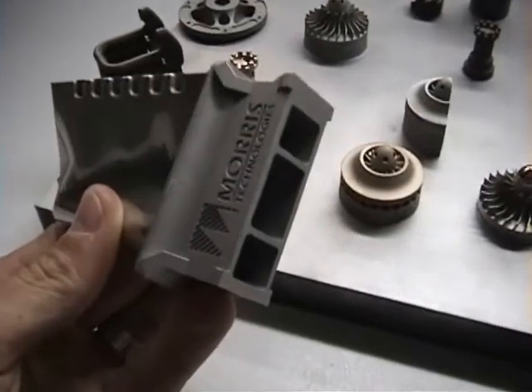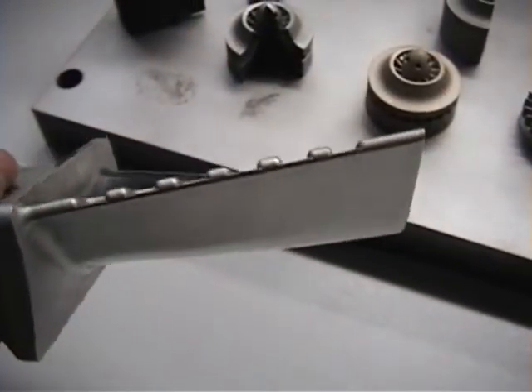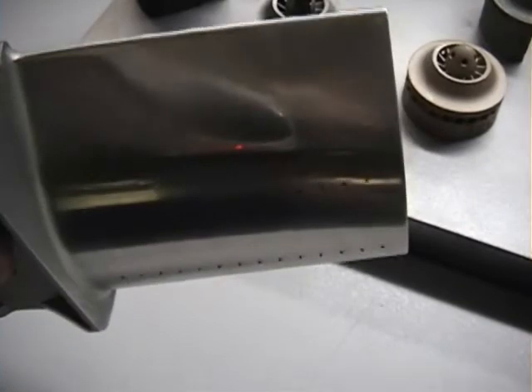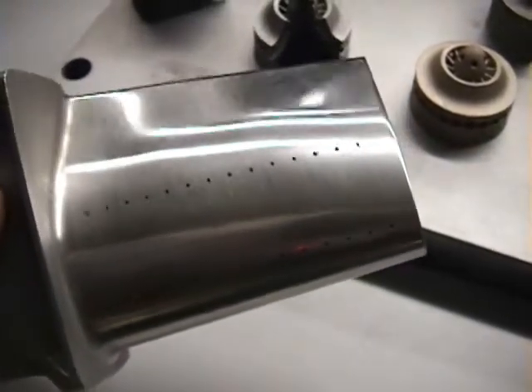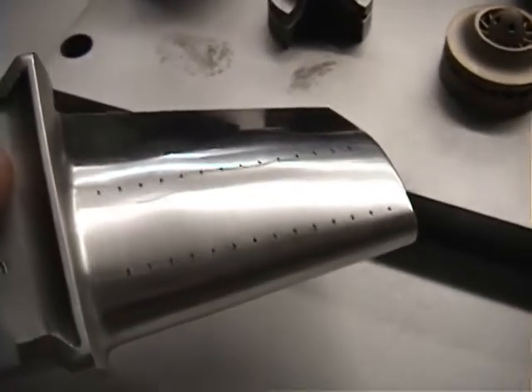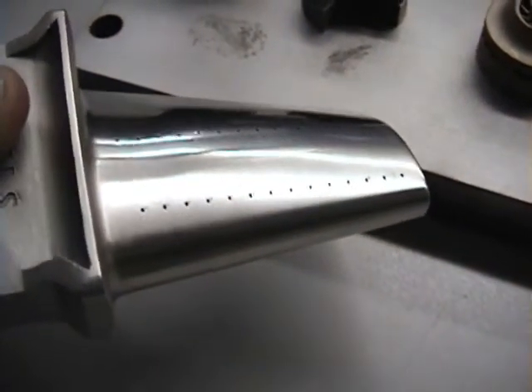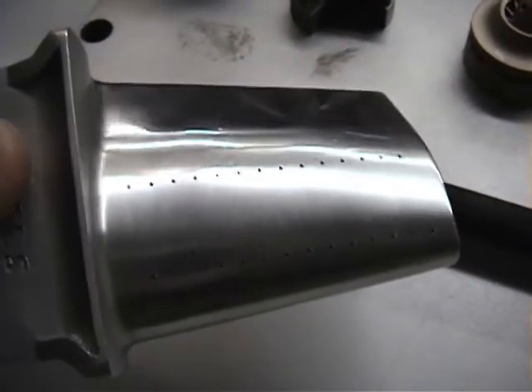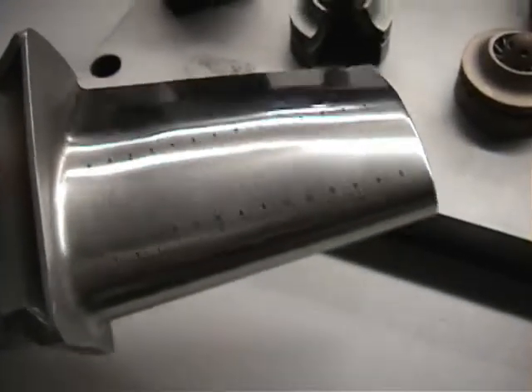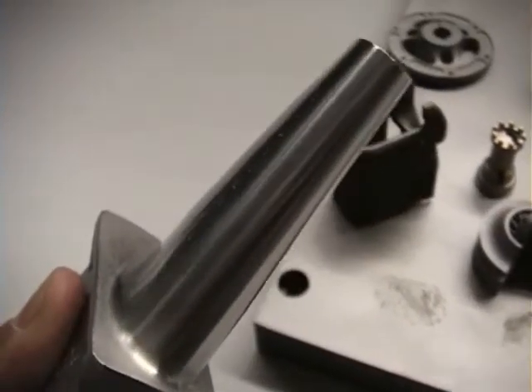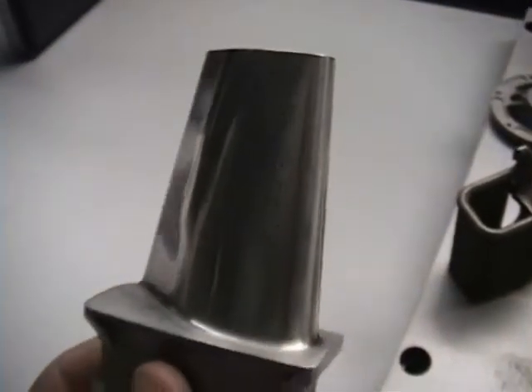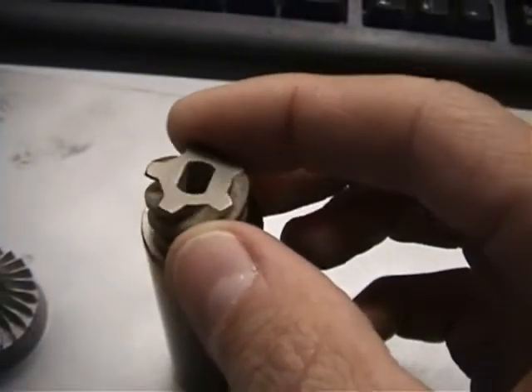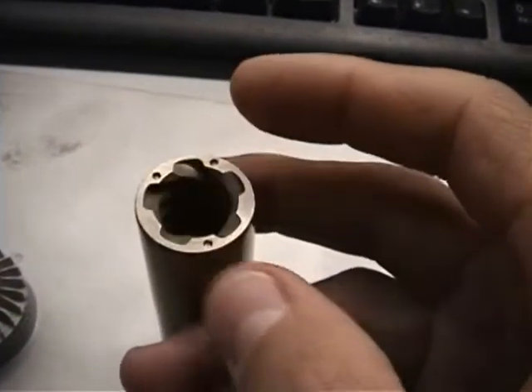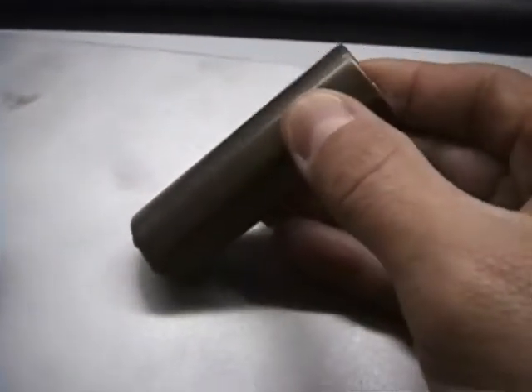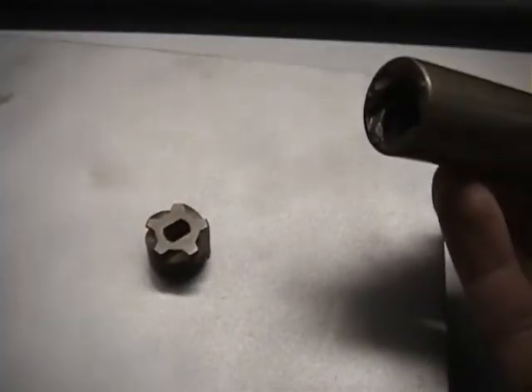It is printed in cobalt chromium, which is considered a super alloy. Notice the detail on the leading edge and trailing edge. These small pinholes help direct fuel and air while the turbine is in operation. Realizing these design details while the part is being grown is one of the major features of the DMLS process. This part was designed with an internal screw mechanism. It would be very difficult to realize this piece with a traditional manufacturing process.